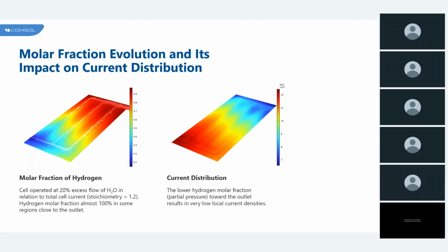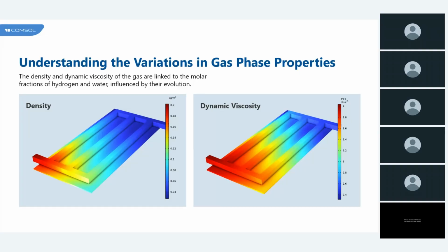So next we will examine how gas composition shifts also influence the thermophysical properties and why accurate modeling of this effect is critical. So in high temperature systems like SOEC, gas properties like density and viscosity change significantly as hydrogen and the steam ratio evolves along the flow path, and this shifts the flow velocity and pressure drop also, and species transport inside the porous electrodes and overall fuel delivery and the reaction efficiency. So if we ignore these effects, we risk underestimating the fuel starvation, local pressure build up or transport limitation. So with the help of COMSOL multiphysics, the gas properties are dynamically linked to real-time composition, making the model more accurate and predictive. So having explored hydrogen production with the SOEC.